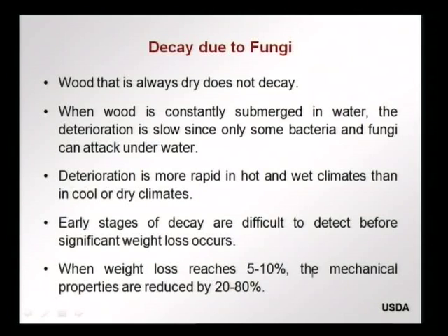The problem with the decay in wood is that in the early stages, you do not really see the damage occurring. And when you detect decay, already significant weight loss has occurred. There is damage which has occurred to the wood, which is too late to repair. And when the weight loss reaches about 5 to 10%, the mechanical properties have already decreased by 20 to 80% in some cases. So, it is very important to keep wood dry and to have wood sealed in hot and wet climates.